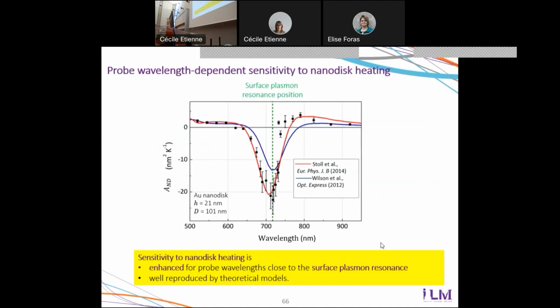As you can see, the absolute value of this sensitivity is very large here as compared to other wavelengths. It's very close to the surface plasmon resonance position. So it means that if we really want to be sensitive to the heating of a nanoparticle, we have to work here. But it can also be zero here or here. It means that here our signals are not sensitive anymore to the heating of the nanoparticles.